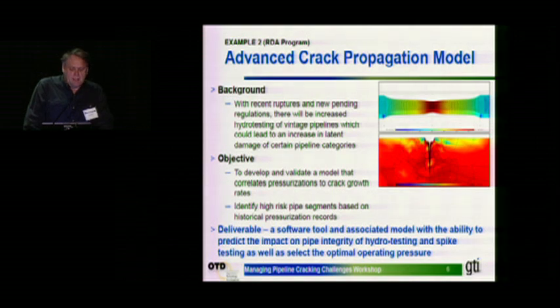And this addresses the increased usage of spike tests and various pressure tests, where there's a concern that the actual test will increase the likelihood of latent damage in certain pipeline categories. So the objective here is to develop and validate a model that correlates pressurizations to crack growth rates, to identify high-risk pipe segments based on historical pressurization records.